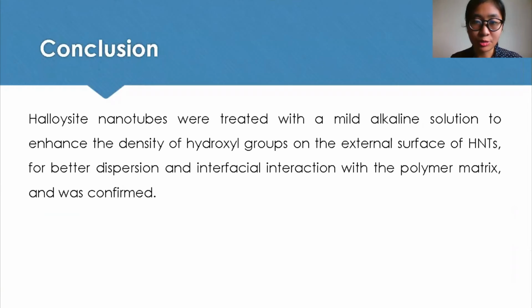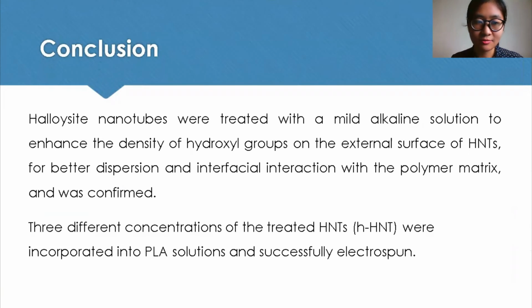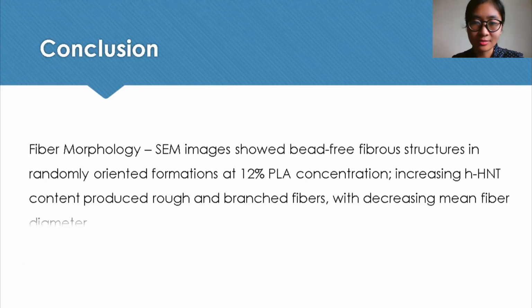All right, so in conclusion, halloysite nanotubes were treated with a mild alkaline solution to enhance the density of hydroxyl groups on the external surface of HNTs for better dispersion and interfacial interaction with the polymer matrix, and it was confirmed. Three different concentrations of the treated HNTs were incorporated into PLA solutions and successfully electrospun. That said, the first objective of this study was successfully met. Then the conclusion for the second objective, which was to investigate and evaluate the potential of the electrospun composite fiber mats as a wound dressing material, are as follows.